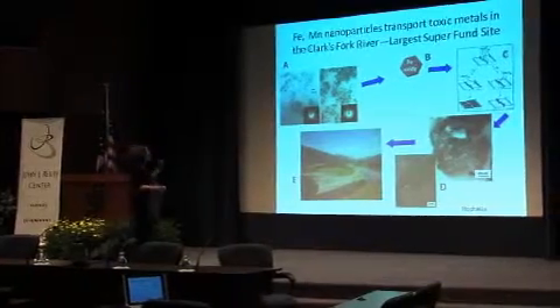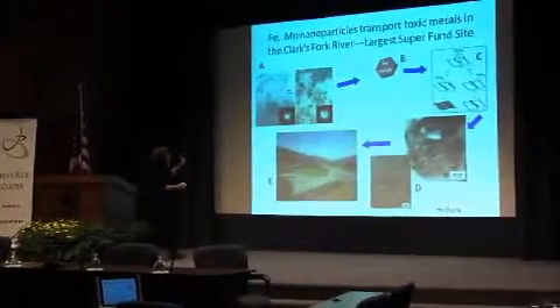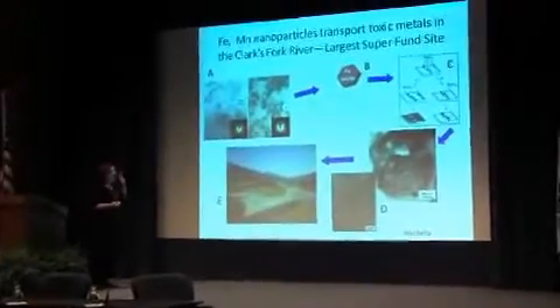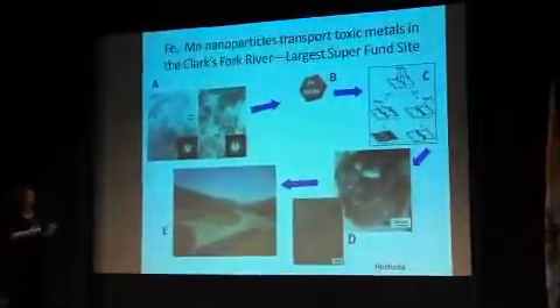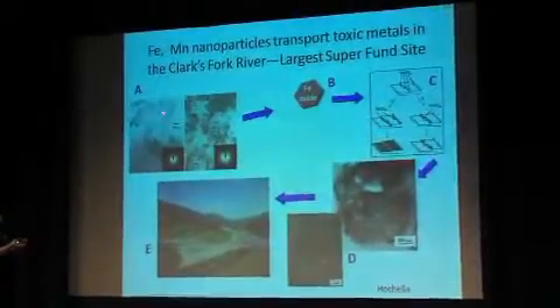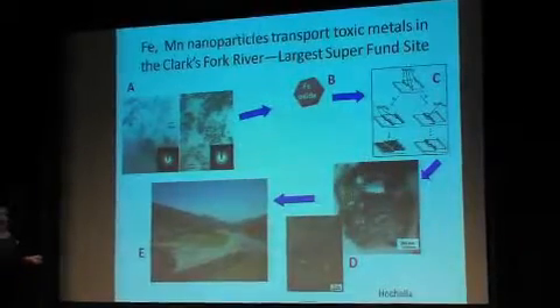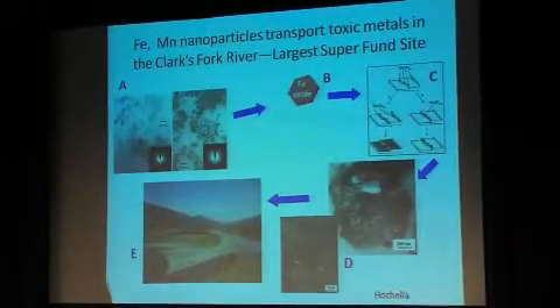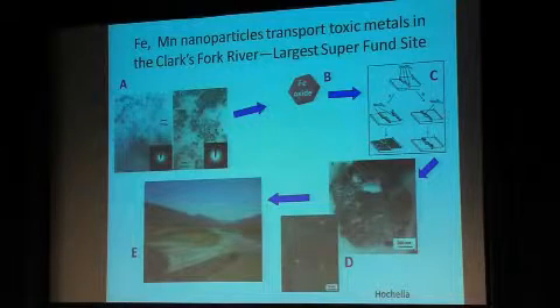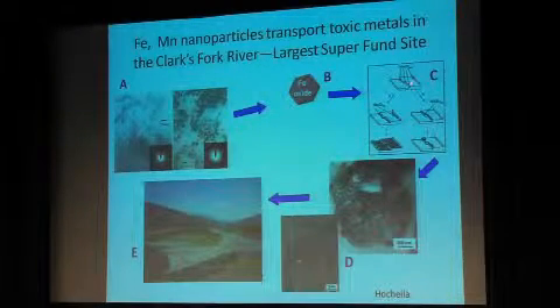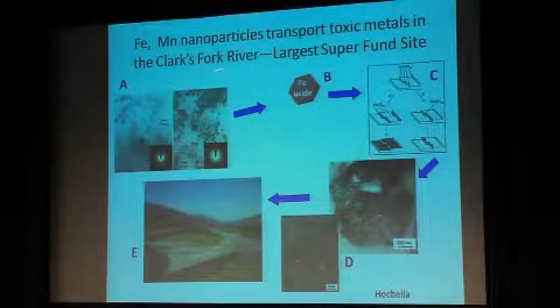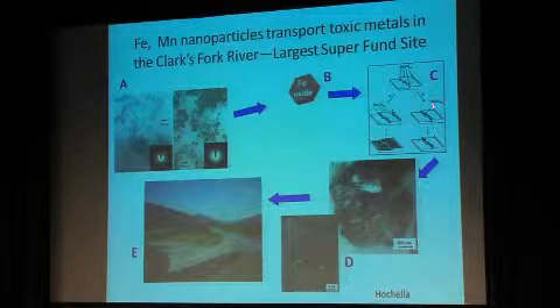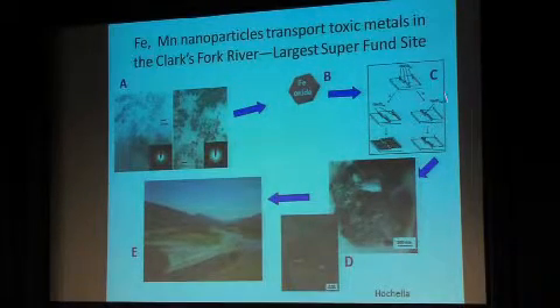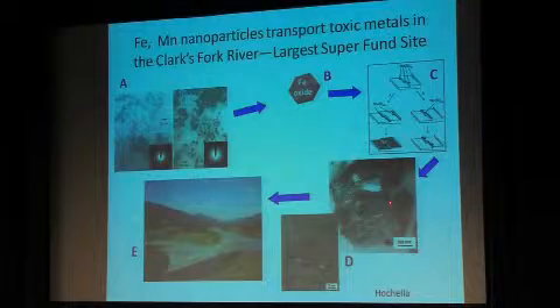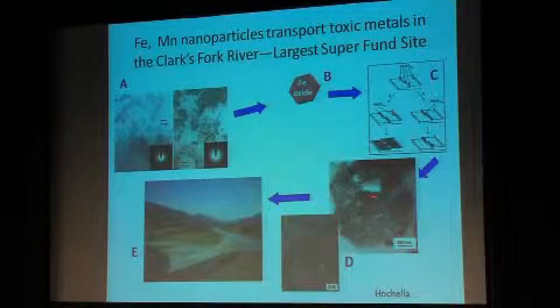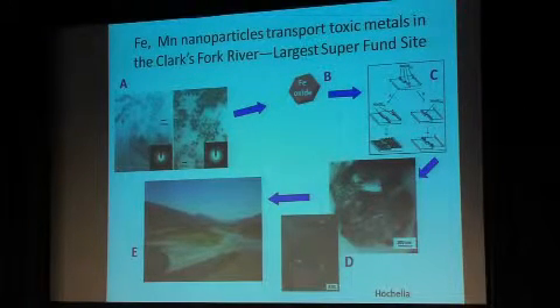At this Clarks Fork Basin site, what he's found on the Clarks Fork River is that what's really controlling the contaminant transport is nanoparticles of iron and manganese oxides. These iron and manganese oxides precipitate in this environment, and they can just transport down the river themselves, or they can attach to different surface site features on other grains, and then you end up with a large particle that has a lot of nanoparticles on it.